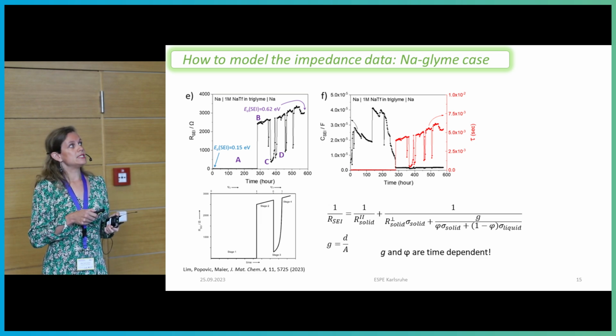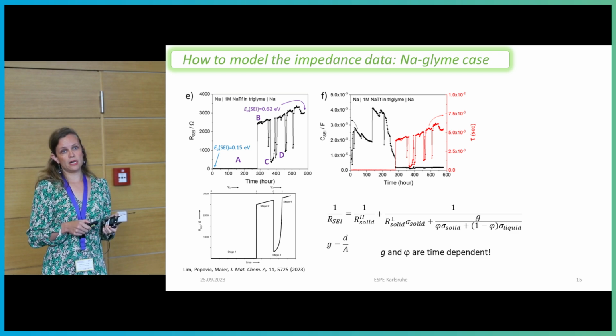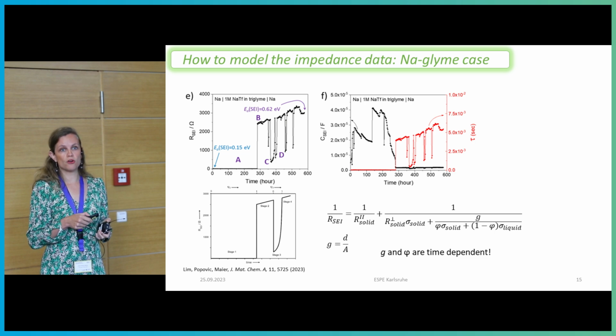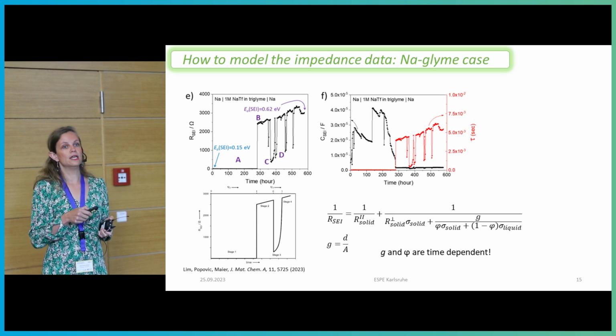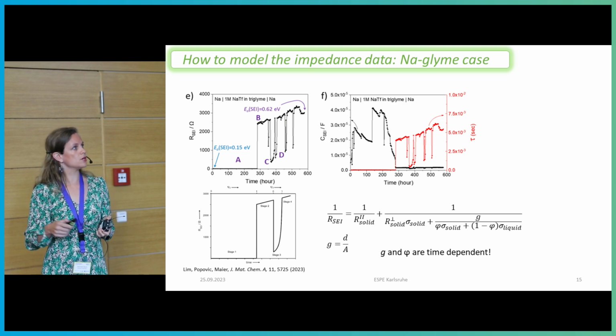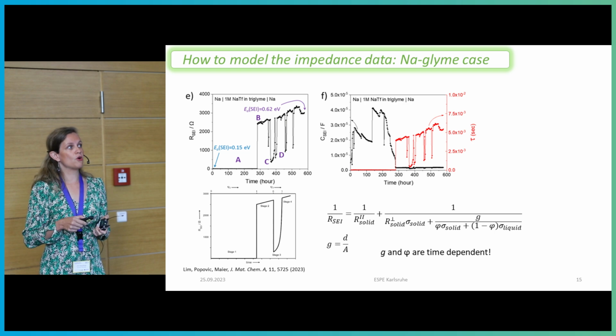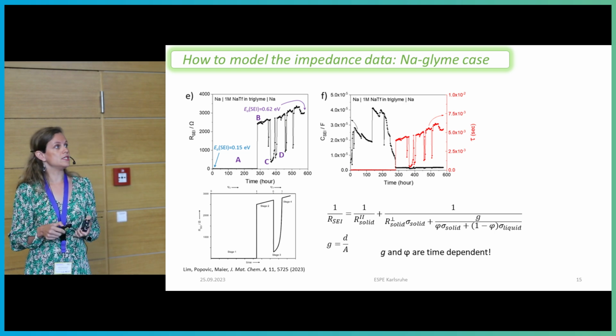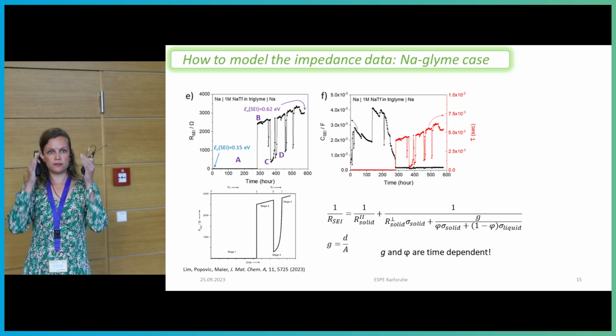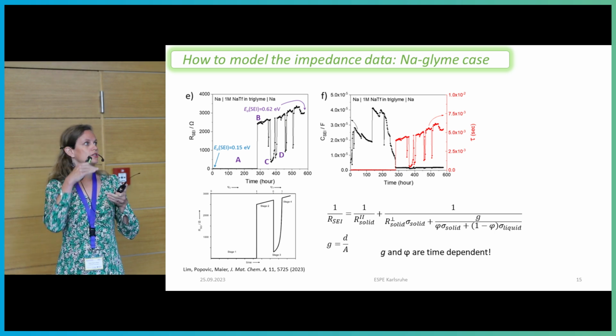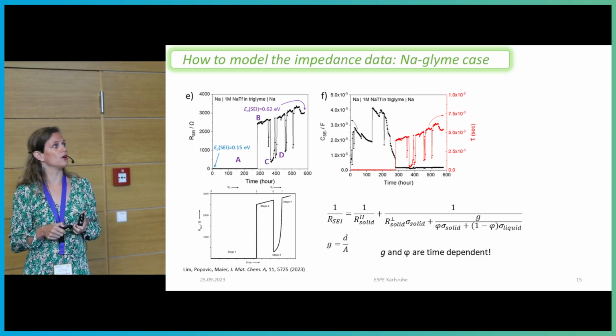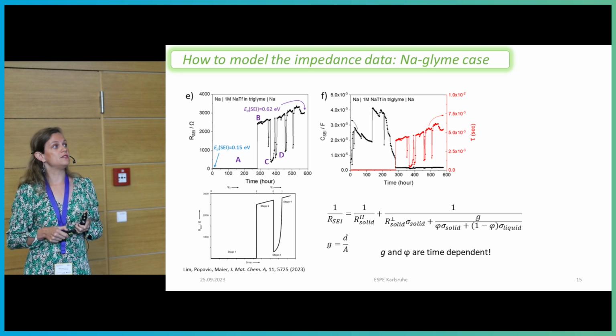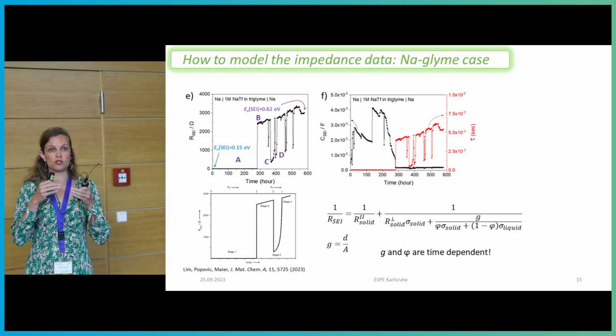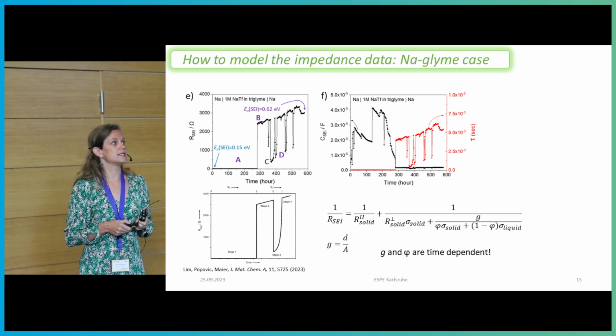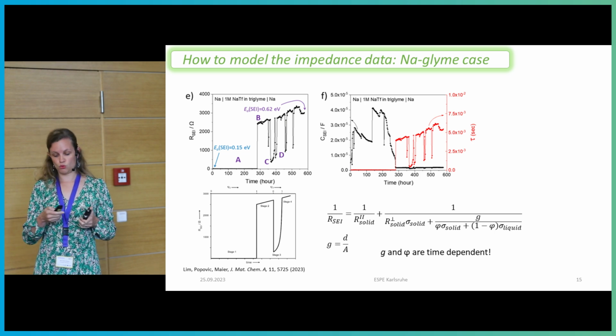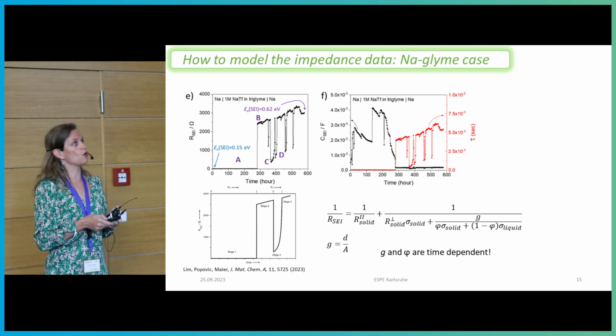So actually, many speculated that this is a very stable SEI at the beginning, and we dare to say that this is actually a very porous SEI with ion transport at the beginning, and then finally with very many mechanical instabilities afterwards. And we can, again, by using the parallel switching model, actually this kind of system where we take into account the resistances of the solid in the initial state and the resistances of the solid in parallel and perpendicular to our liquid. And then, of course, if we take these geometrical parameters and the volume fraction of the solid that is filling in the SEI as time-dependent parameters, then it's easy to actually parameterize this kind of growth.